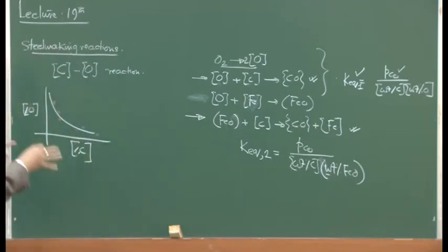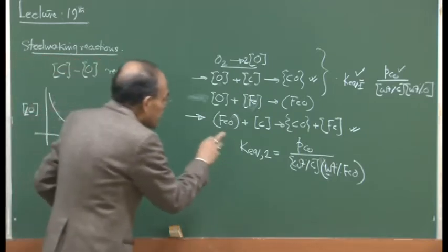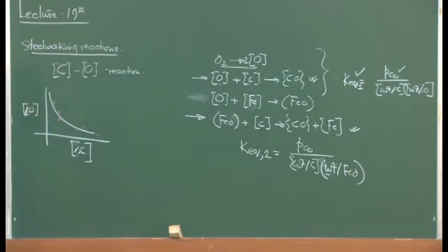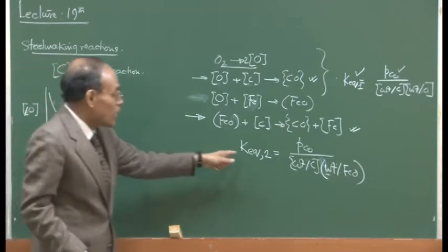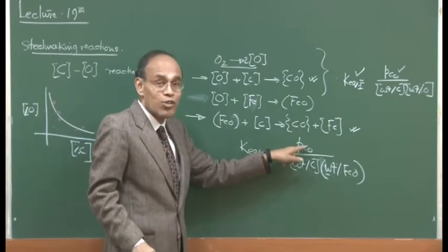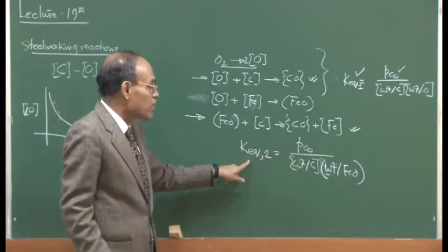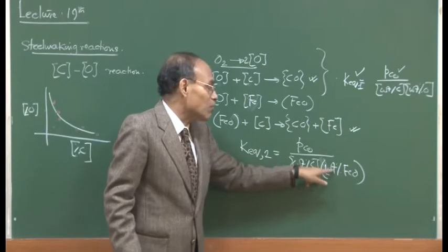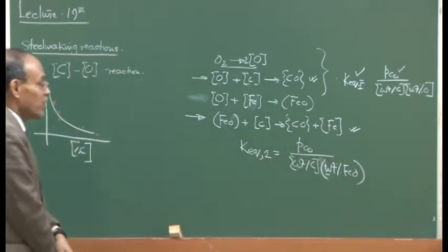So I am assuming that there is a gas metal equilibrium, and if we extend the hypothesis that there is also a slag metal equilibrium in the system, then I would also conclude that corresponding to this carbon, this oxygen in the metal, there has to be a fixed activity of iron oxide in the slag phase itself. So this equation will essentially tell us that if we put PCO as a fixed pressure, this equilibrium constant is constant. Therefore, wt% carbon multiplied by wt% FeO in the slag has to be a constant.